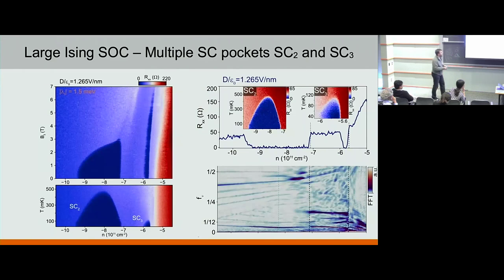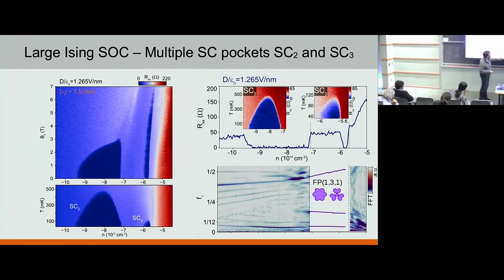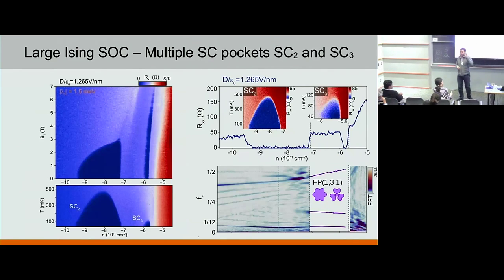So I'm just going to give you results, and maybe we can discuss how we got these results. Essentially, you can map the lines at various displacement fields and various dopings, and you can take different ranges of magnetic field which you use in the Fourier transform to identify the main lines, okay? Some of these lines are real, some are just harmonics, okay? It turns out that in this particular region you have one big pocket, then three medium-sized pockets, and then one very small pocket. So we have additional evidence that this is most likely some sort of an intervalley coherent state.